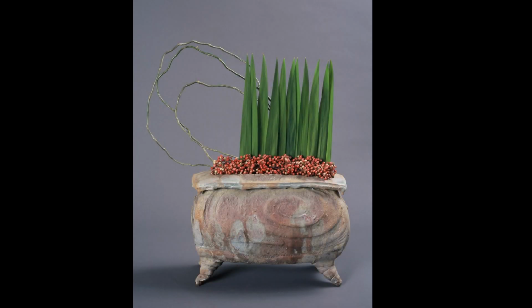And this piece is interesting. It has nothing on the outside, but it's lined with Leach's Oribe glaze, the copper green glaze, and that pink color is from the copper migrating through the body of the piece during the firing and coloring, giving a pink-purple blush. Now, when you use Leach's Oribe, the copper is one of the first elements to vaporize in a kiln, and so any copper glaze that you use will also turn pieces downstream of your piece, pink and sometimes red, purplish colors.